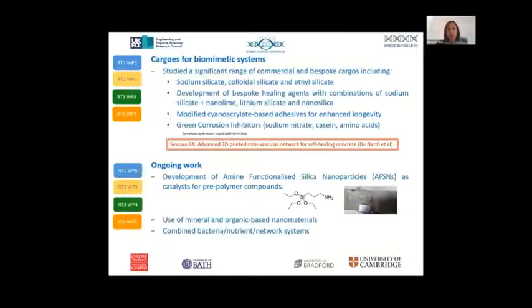One of the other alternatives that we're looking at is these expansive agents, so we can hold them within our networks and use catalyst particles that are distributed within the concrete or cementitious matrix that will help our polymers, our healing or sealing agents, to react at speed, to fill a crack, which we can then use some other techniques such as our crack closure techniques to address the recovery of strength if we so need.